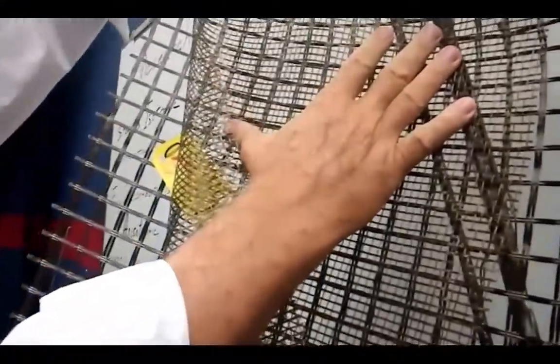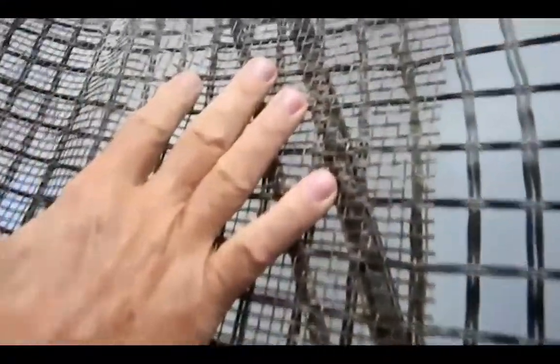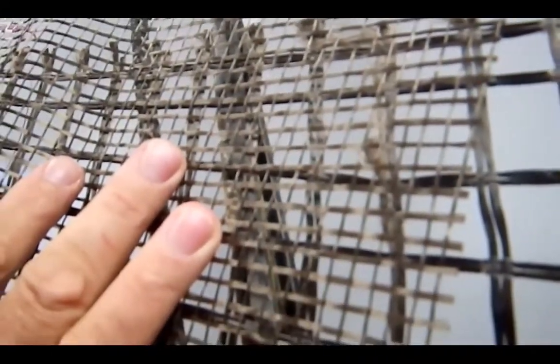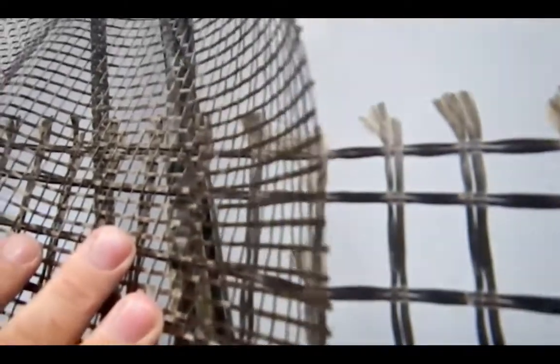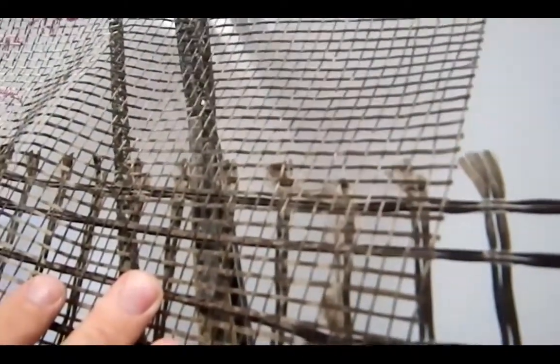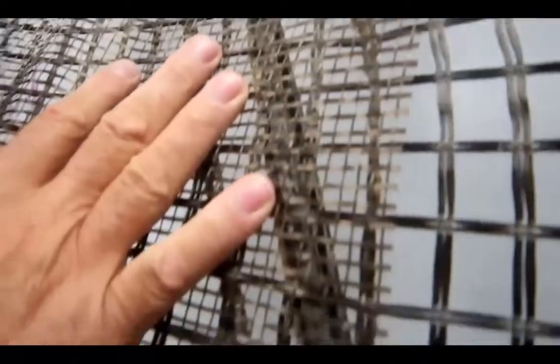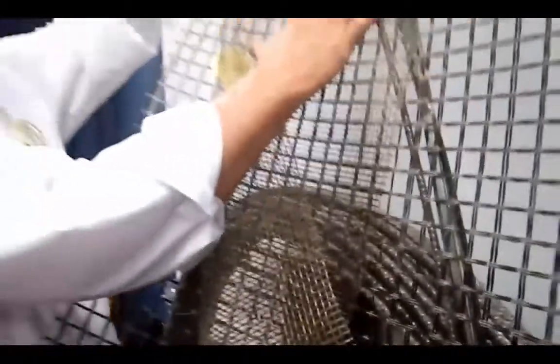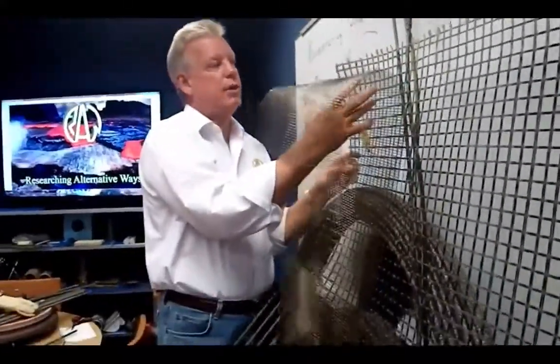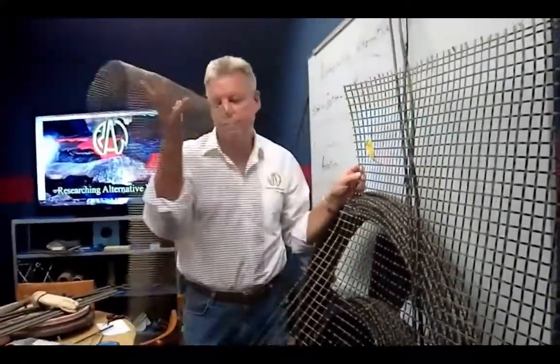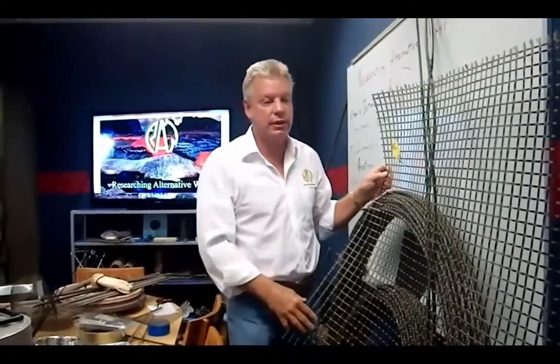This material was something that was developed for SIP panels, structural insulated panels, mag board, MGO board. That industry had an issue with their MGO board was so strong that they had a difficult time taping the joints. It exceeded what fiberglass could do in tensile when they had thermal swings. So we developed a tape made of basalt, and basalt being stronger and having better adhesion to the cementitious materials than fiberglass solved that problem.